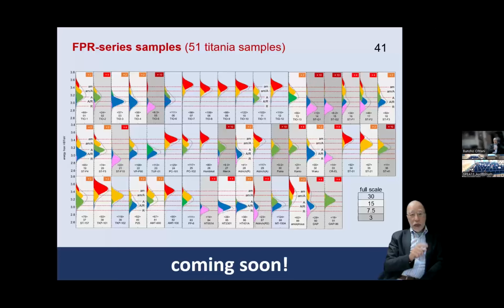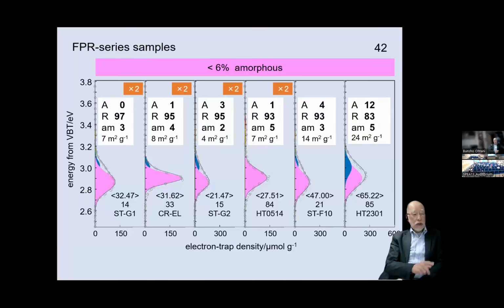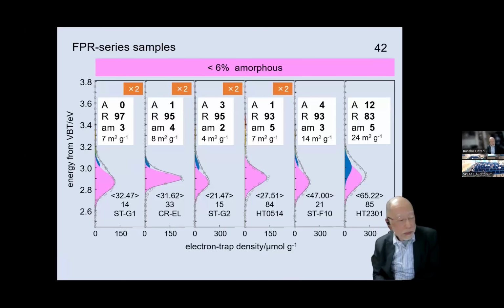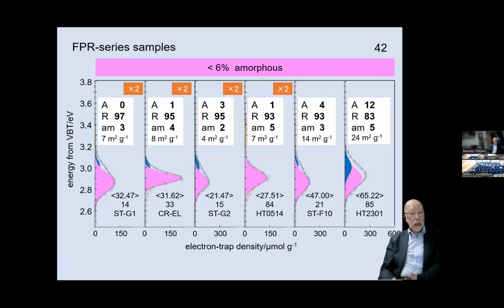But a small part of amorphous is still on the surface. So therefore, almost no sample, pure anatase and pure rutile sample, can be obtained. And for real samples, this composition, anatase, rutile, amorphous composition, is calculated by XRD.